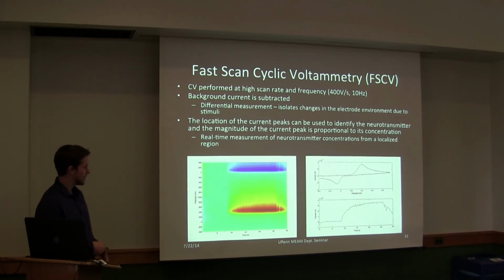So this is a typical fast scan cyclic voltammogram, where the current is the pseudocolor. Red would be a positive current, blue would be a negative current. These streaks correspond to the oxidation and reduction of the neurotransmitter dopamine. The y-axis is the potential that we're scanning. It is actually a triangle wave, so it goes from negative 400 millivolts to 1 volt and then back down. So we're essentially plotting the potential on the vertical axis, the time on the horizontal axis, and pseudo-coloring the current. These streaks correspond to dopamine, and the location of these peaks is how you can indicate that it's dopamine.